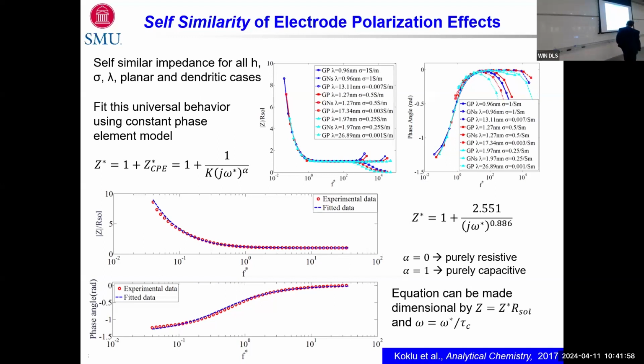You have to add 1 on it, which means that this behavior should be true regardless of the size of the electrodes and the electrode separation and the conductivity. You can work backwards to actually put dimensional numbers to it. All right. So by working backwards, you can have a good idea of how much this effect in your electrode is going to take over. And if you know that beta dispersion happens around, say, 300 kilohertz or so, you don't want this to be coming and shielding that kind of behavior.